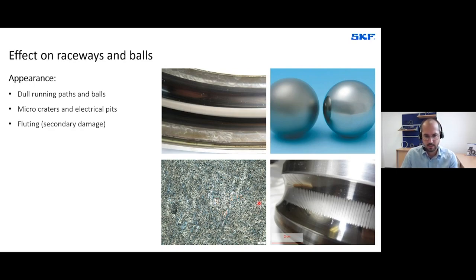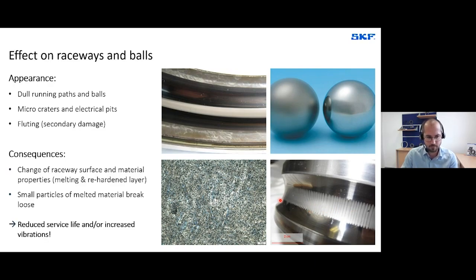And in a very extreme case, you get this fluting appearance, you get the washboard pattern, but this is actually a secondary damage. And besides those visual effects, it also has performance consequences on the bearing. It changes the raceway surface properties and the material properties. It can tear out material particles of the molten material, which break loose and contaminate your lubricant. And all this is reducing your bearing service life. And it can also cause increased vibrations. Basically, both you don't want to have it in your machine.